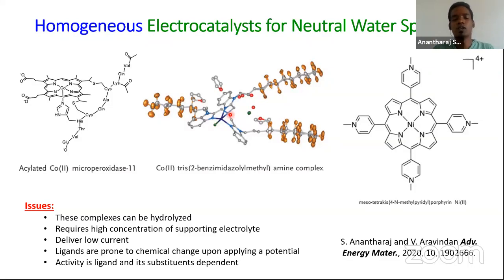But this problem was in recent years overcome by making ligands with high hydrophobicity, which means that the amount of water molecules that reach the metal center is strictly limited by the hydrophobic environment of the ligand, which means that water molecules can approach only the coordinating position, this position and this position, and can undergo further reaction corresponding to water oxidation instead of hydrolyzing. So that's how this problem was recently overcome.